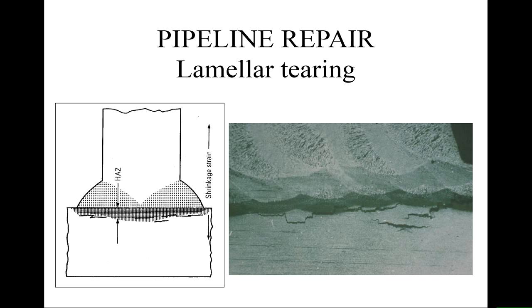weld. So just to show you what lamellar tearing looks like, this is a full penetration fillet weld, but you've got now welding from this direction. You can see that the penetration depth here is right to the middle, and you've got this region here which is under a very high tensile stress due to the contraction stresses as this cools. And then these are the lamellar tearing cracks that you're getting just in that region underneath the heat affected zone in the plate that's been welded onto.